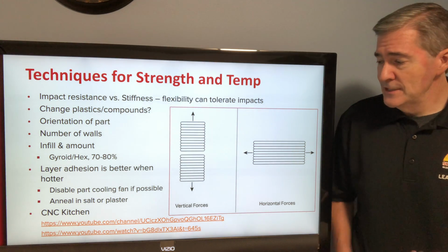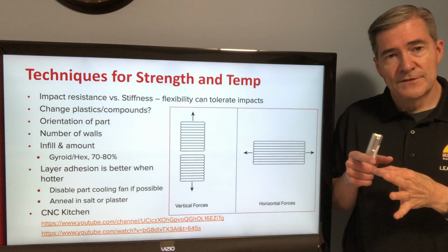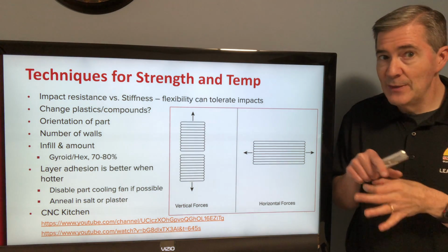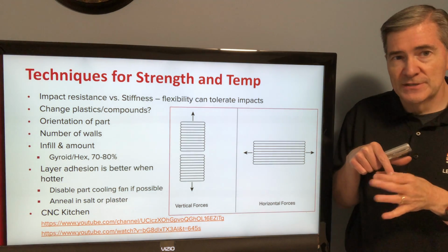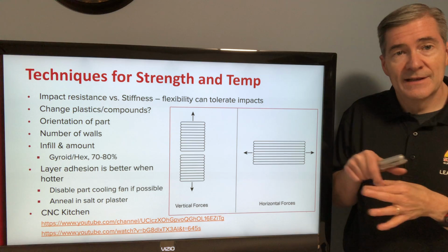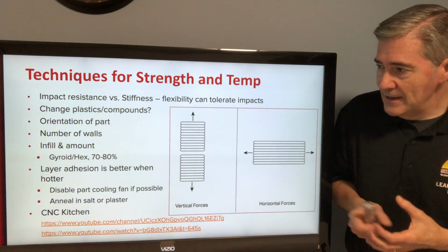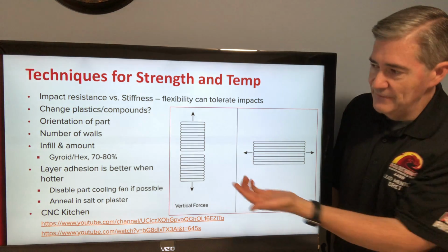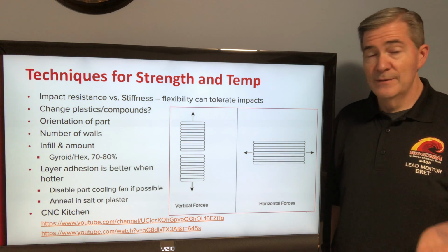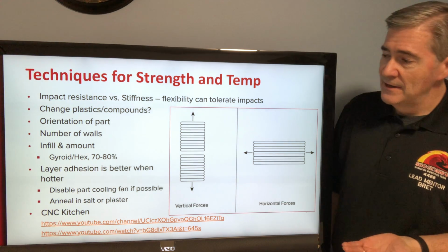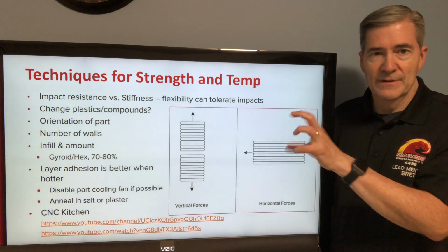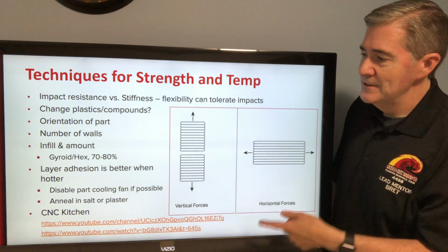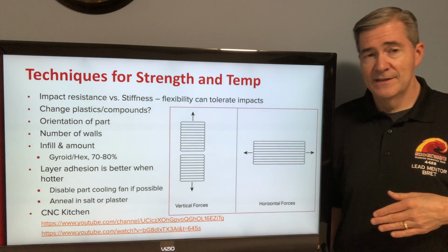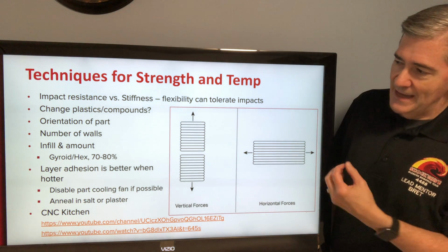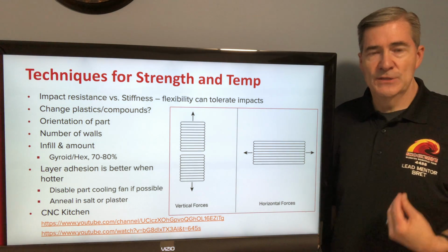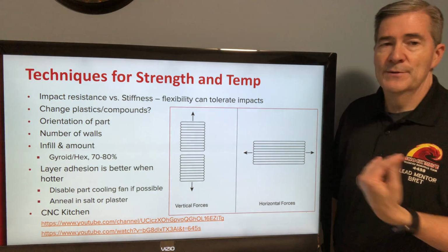Other things you can do is you can add more wall layers. So usually there's like 2 or 3, maybe 4 wall layers at the outer dimensions, but you can add more and it gets stronger up to a point. And then also you can add infill. Generally speaking, 100% infill is actually less strong, depending on exactly what kind of forces, but generally you're going to be better off with 70 or 80% infill of some kind, like a hex or a gyroid infill. Those are some of the strongest ones. That's going to be better than 100% infill.